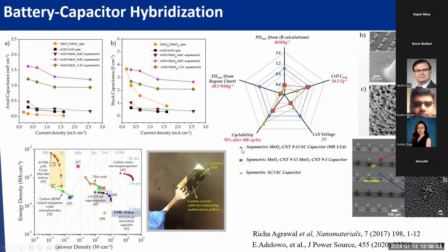And you can see from this spider chart, typically when we compare asymmetric and symmetric supercapacitors, in this case, we also compare with AC typical capacitors. We found out the asymmetric system actually can give you a much more balanced effect compared to the symmetric system. But for the symmetric system, in terms of AC, the cyclability is the best. But compared to, let's say, energy density and power density, the symmetric AC system, or even a symmetric pseudocapacitor setup, the energy density is much lower than the asymmetric system.